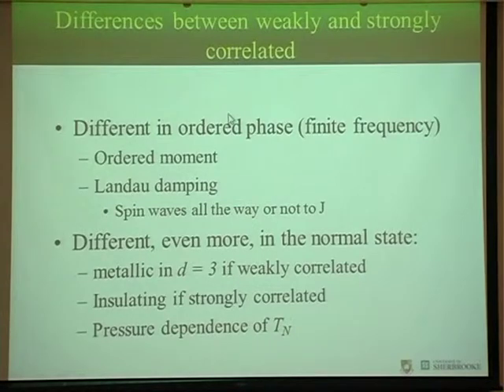Now there's a difference between weakly correlated and strongly correlated systems. They have the same emergent properties, but as soon as you move from asymptotically low energy, there are differences. The magnitude of the ordered moment is different. Landau damping will kill spin waves before we get to J. And in the normal state, they are even more different. In the weakly correlated case, the normal state is metallic. In the strongly correlated case, it's insulating. And the pressure dependence of the Néel temperature is different.